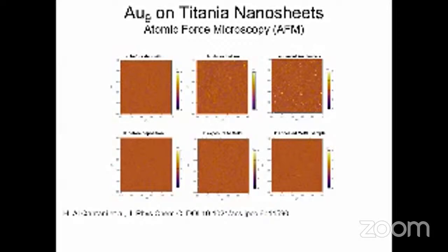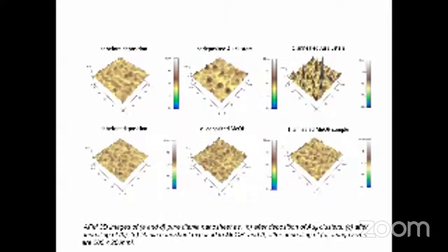And the lateral resolution of AFM is showing the cluster size for our Gold 9 nanocluster. We saw quite a lot of aggregation after annealing. This is related to removing the ligands and letting the nanocluster organize itself to end up on different sizes.